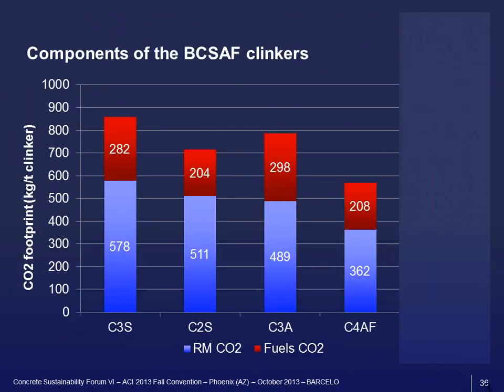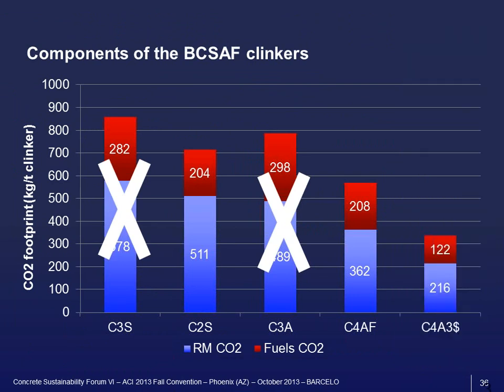So how can we achieve such a performance? So you see that C3S and C3A, they were the phases with the higher CO2 footprint. We don't have them in this cement. So instead, the main phase is C2S. We have a little bit of C4AF, and we have a significant amount of this calcium sulfoaluminate phase. And you see that the CO2 footprint of this phase is very, very interesting, both on the raw material CO2 and on the fuel.